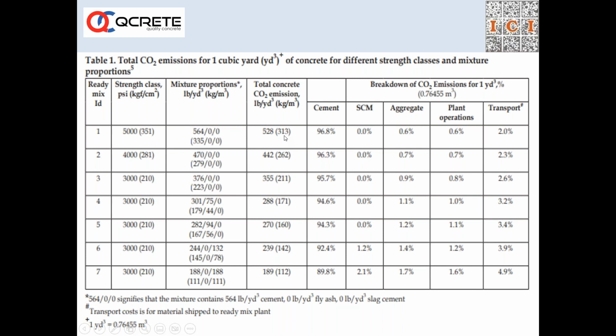And if we go to 282 kgs of cement and 94 kgs of fly ash, it comes down from 313 kg per cubic meter to 160 kg per cubic meter. And when we go to the same mix, let us say here 376 kgs of OPC, now 188 OPC, 188 GGBS, it has come from 211 to 112, almost 50% reduction in the carbon dioxide emissions.